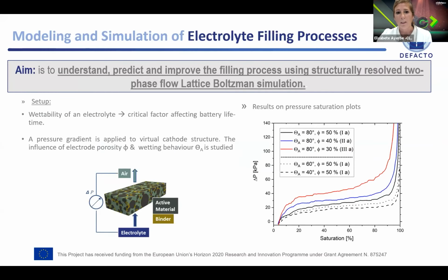Now, coming to the electrolyte filling, the aim is to understand this step properly, because it's a very time-consuming step. And there are certain parameters, like the wettability of the electrolyte, which is a critical factor that affects the durability of the cells. So we need to properly address this factor in order to enhance the lifetime of the cell.